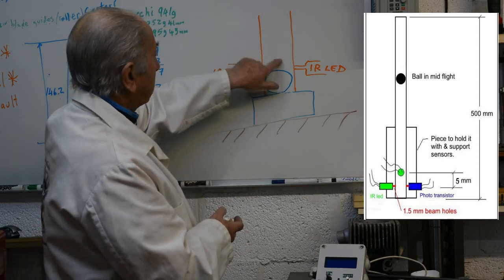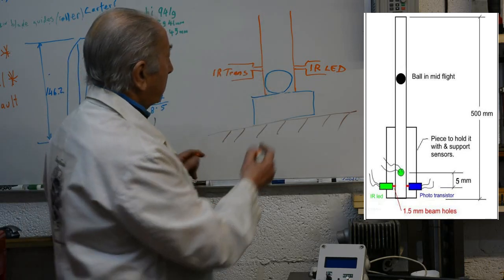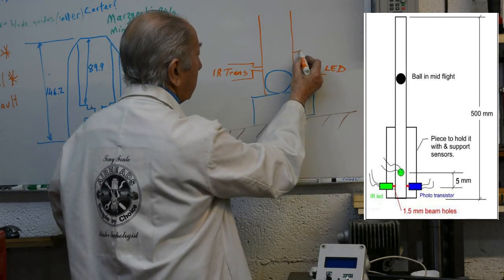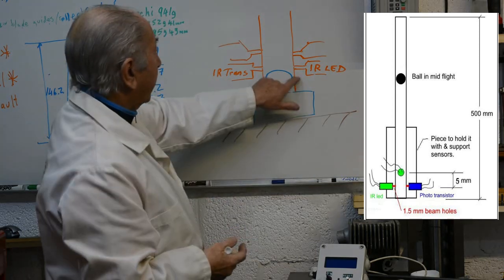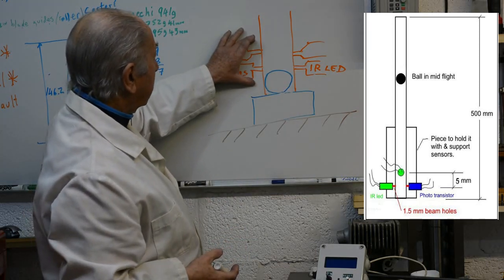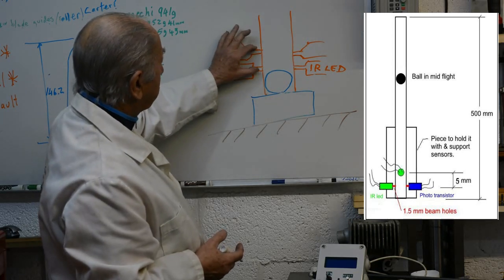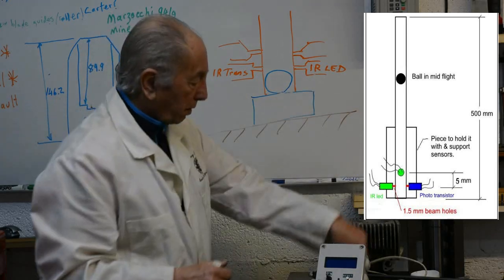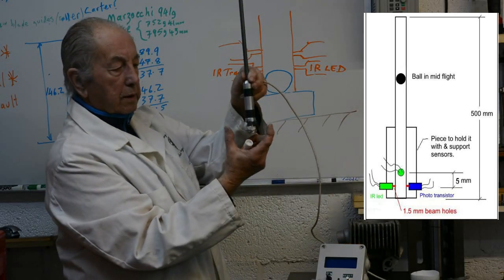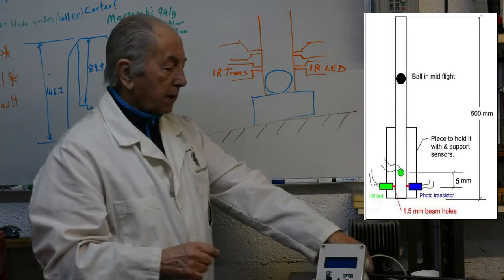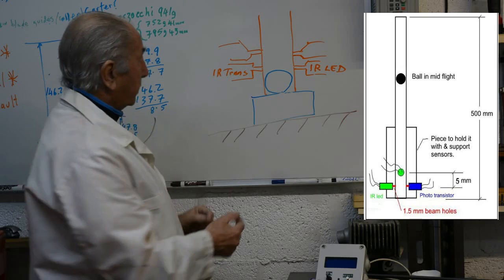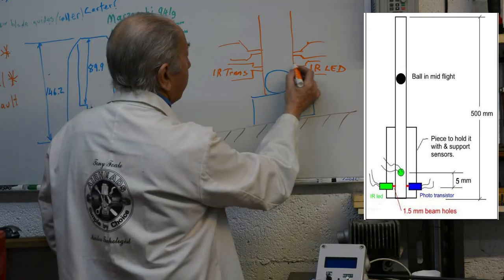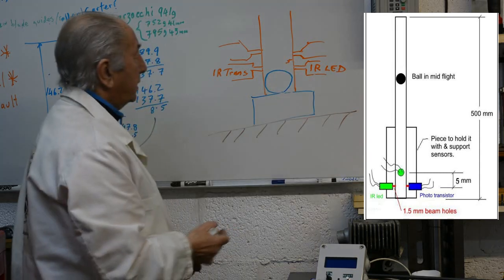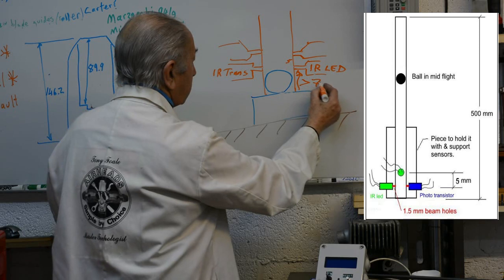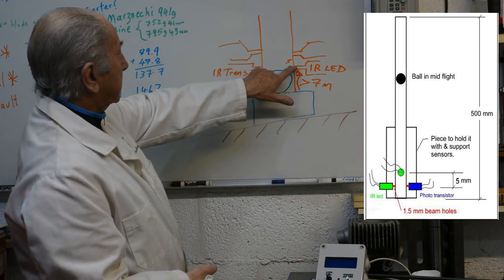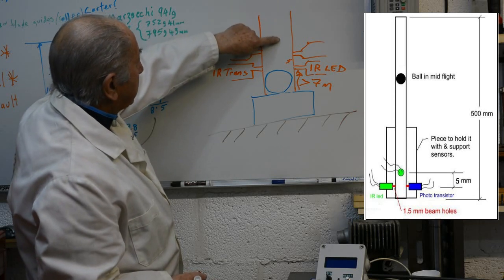But I can't just measure the velocities with one, so I put in a second one up here in the same way. Now, if I'd actually stacked them as I've drawn it here on a two-dimensional plane, I wouldn't have been able to get these close enough together. So what I've done, one lot goes this way and the other lot goes that way. So then they can come as close together as necessary. So I've got approximately 5 millimeters between these, and this is up greater than 7 millimeters, so that when the ball's at the bottom, it's clear from here. The ball comes down.